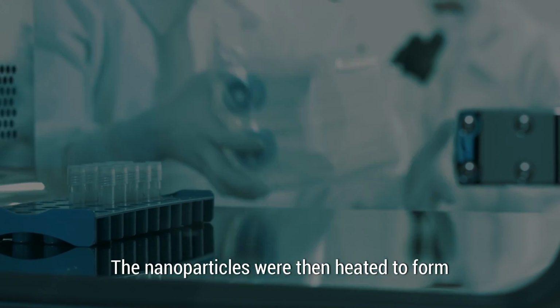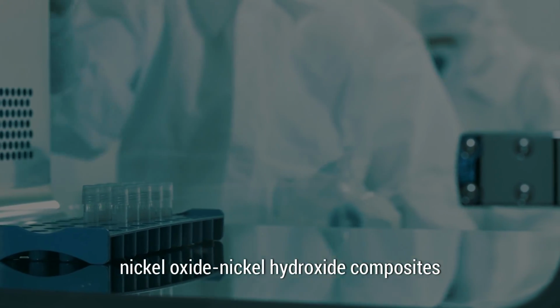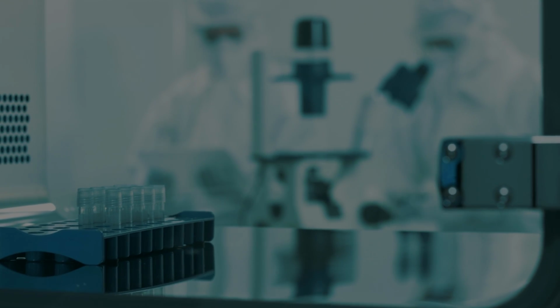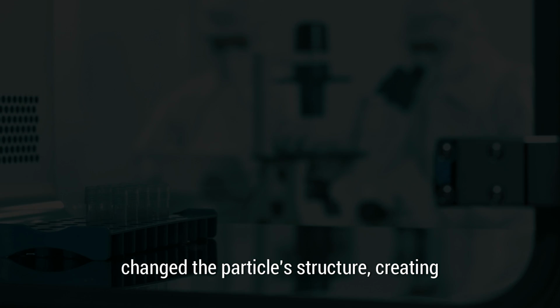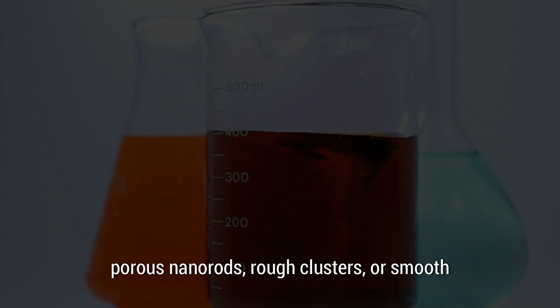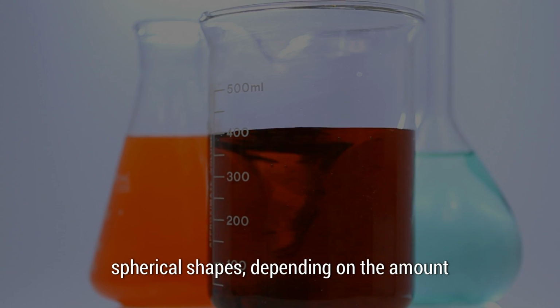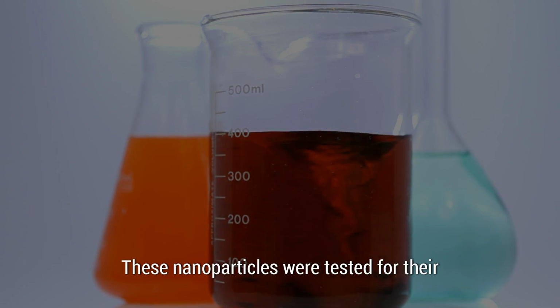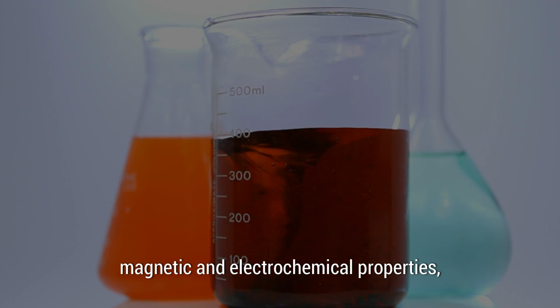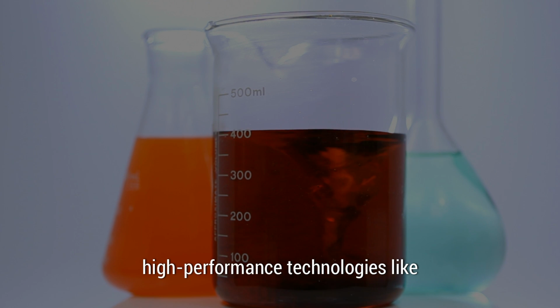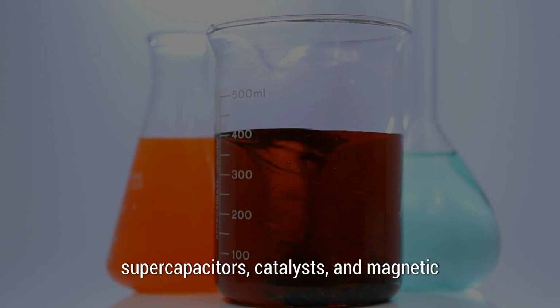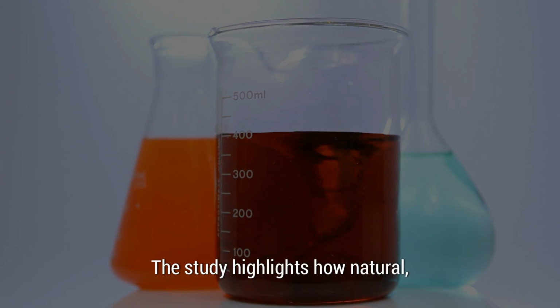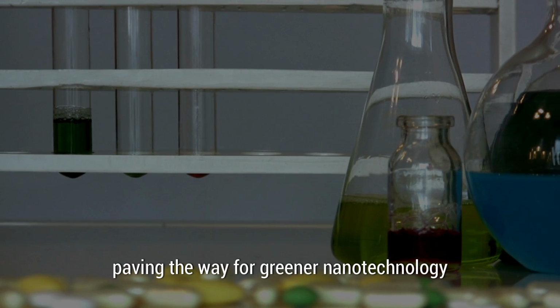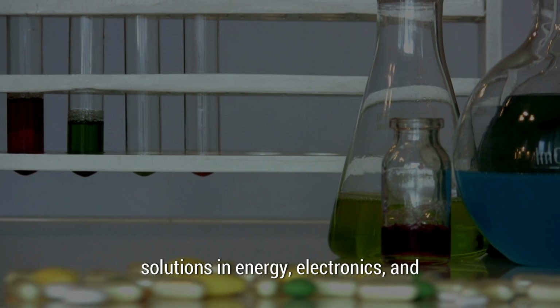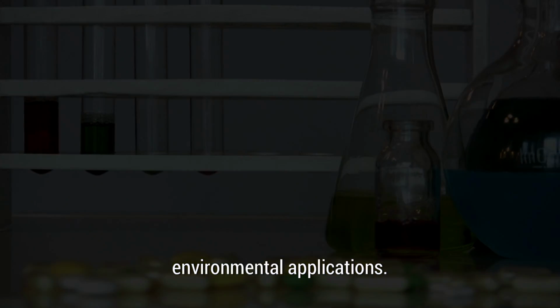The nanoparticles were then heated to form nickel oxide nickel hydroxide composites with different cobalt concentrations. The results showed that cobalt doping changed the particle structure, creating porous nanorods, rough clusters, or smooth spherical shapes, depending on the amount of cobalt added. These nanoparticles were tested for their magnetic and electrochemical properties, showing potential for use in high-performance technologies like supercapacitors, catalysts, and magnetic storage devices. The study highlights how natural, sustainable methods can produce advanced nanomaterials with improved functionality, paving the way for greener nanotechnology solutions in energy, electronics, and environmental applications.